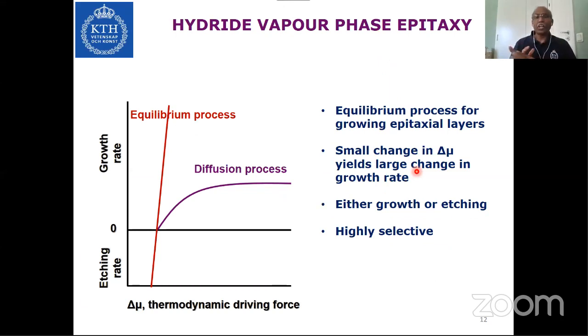So why is it an equilibrium process? You say it is an equilibrium process, but why does it have a high growth rate? Because in an equilibrium process, you have a thermodynamic driving force, and here is the growth rate you can call. The equilibrium process grows straight up, whereas the diffusion process will go up when you increase the delta mu, and then it will planarize, kind of stop here. Whereas this one will keep on growing because it is an input controlled process. Okay.